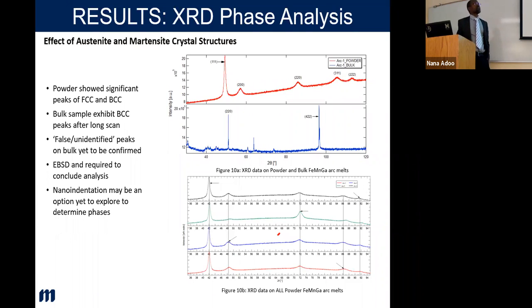And so the same procedure was tested for the arc melts, and you could see a mixture of phases also. So to get a clear understanding of what was going on, the bulk samples were milled. I actually milled them so we could have them in small sizes, because of texture in the arc melt, you could not have some of the reflections showing. So the powder was a method to get every one of the peaks showing. But surprisingly, all the peaks that showed there matched an FCC, which was not definitive.